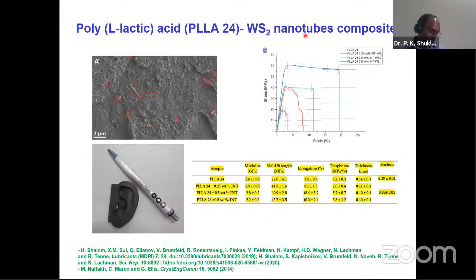And if you add the nanotubes, it becomes as strong as 60 megapascal, and the elongation can go as much as 15%. And the fracture toughness of these materials is enormously larger compared to the original material. The toughness in the pure PLLA is 1.2, and here it's almost 4, which is a factor of 3 or 3.5 larger. So this gives a very big advantage for many medical products. And indeed, now we have several collaborations with medical companies to try to develop products based on these materials.